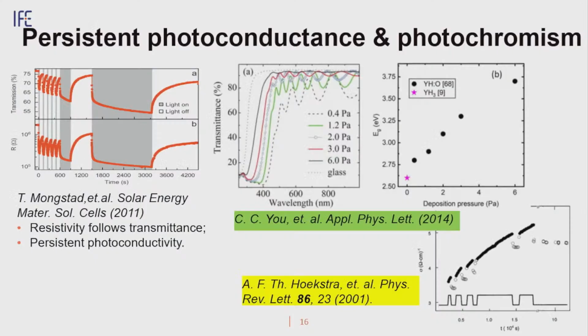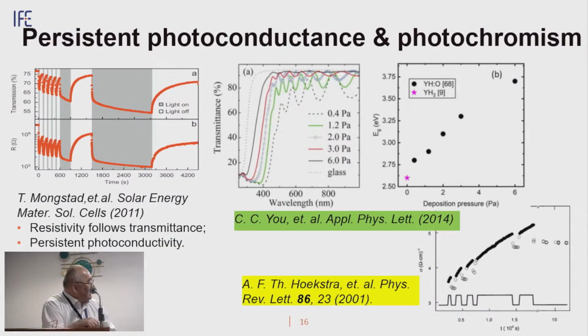But when we started to tune the hydrogen deposition pressure, we found that the transmittance spectra was shifting. I thought it could be stopped when it comes to the band gap of yttrium trihydride. But it didn't stop. It started to shift toward lower wavelengths as well. It means we are dealing with additional oxidation as well. It means that the initial hydrogen deposition pressure is somehow influencing the oxygen amount. Then we published our first article with the postulate that oxygen and hydrogen concentrations in the films are anti-correlated. And to prove that postulate, we needed ion beam analysis.